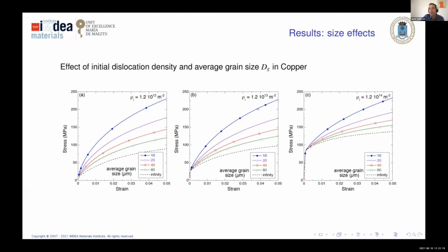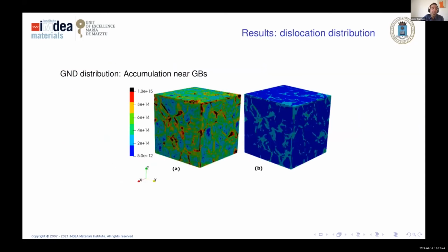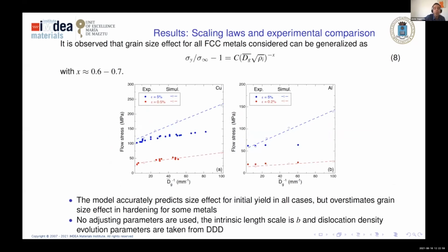Okay, we obtain, as expected, the typical grain size effect: smaller is stronger. We see first one very interesting item, that the larger the initial dislocation density, the smaller the size effect that we have. Why? Because we collapse the Kocks-Mecking law much earlier when we have a larger initial dislocation density. Where do the GNDs go? They go to the grain boundaries. That's where we have the largest gradients. That's where they accumulate. And since they accumulate there, the dislocation density cannot grow more, but we have stronger points near grain boundaries.